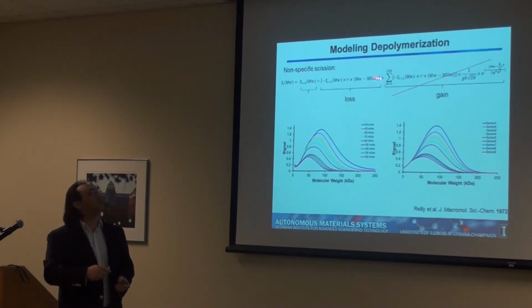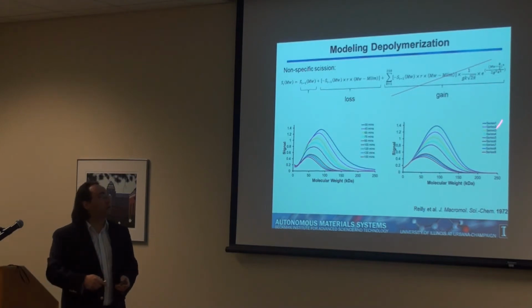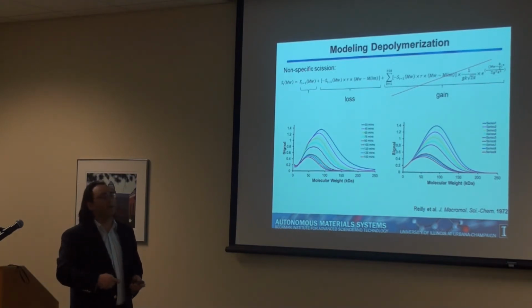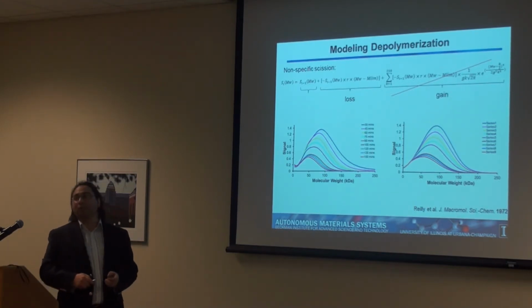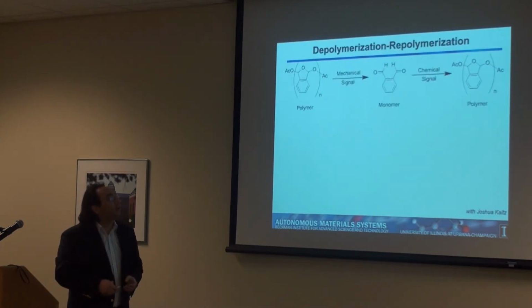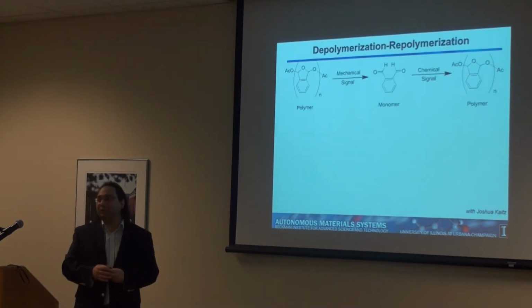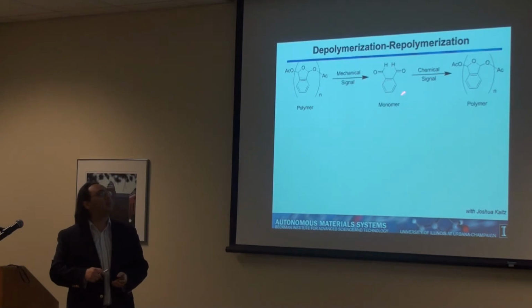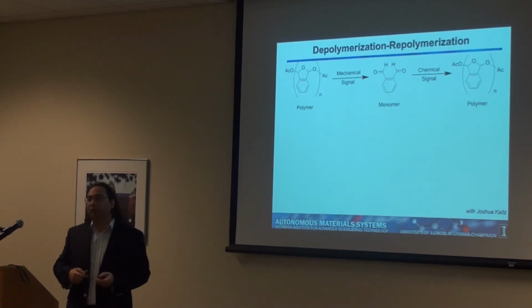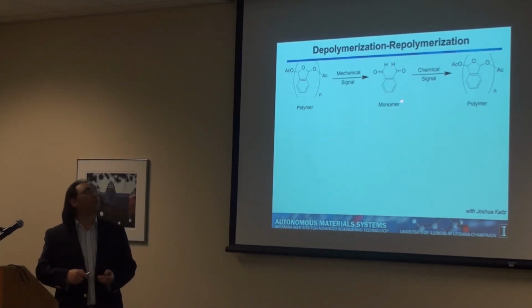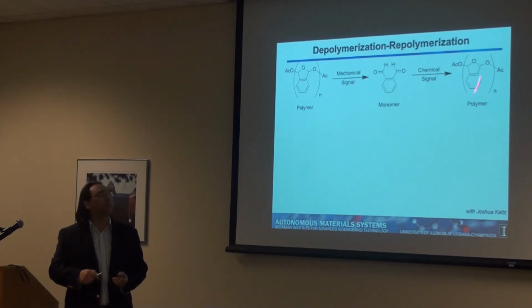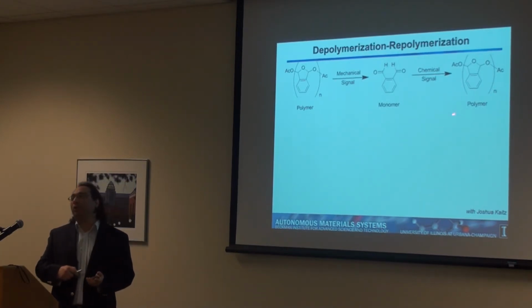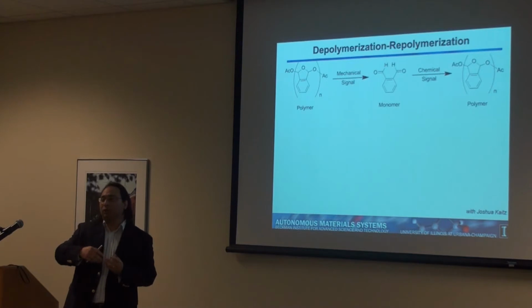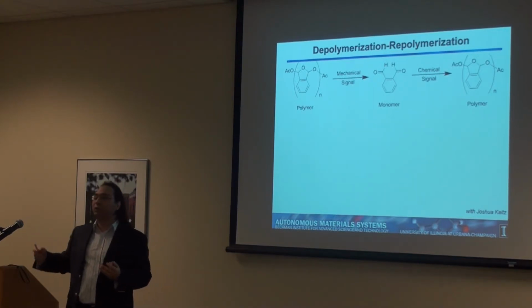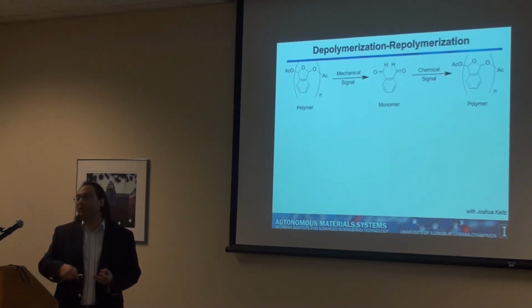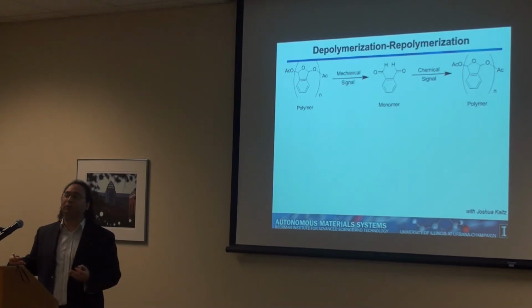So you just use a simpler mathematical model, and when you make this one and compare it to the experimental data, it fits quite well. Now, an interesting thing about this system is that, as I said, it depolymerizes to the monomer. So there is something very nice that we can do, which is that we can repolymerize it. So we are producing a monomer in one place, maybe, so we can move it to a different place, give a chemical signal, and repolymerize it in a different place.